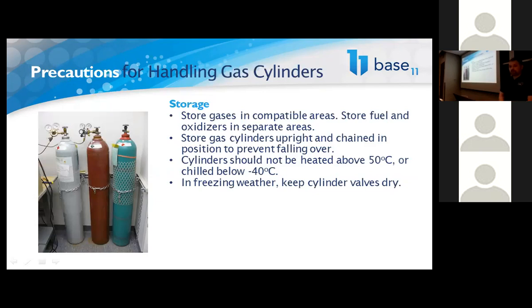When you're storing them, they should be chained upright so that they can't topple. You want to make sure that they don't get overheated. So typically they'll say don't heat them above 50 Celsius. They usually also don't like to get very cold. They are carbon steel, and carbon steel does tend to get brittle at low temperatures. So if you ever were thinking of chilling one below minus 40 Celsius for some reason, don't.